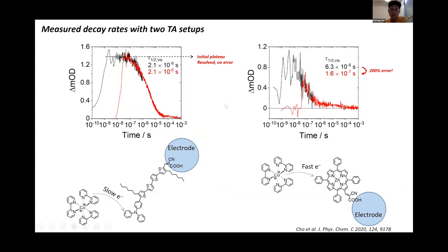This model was tested using actual donor-acceptor pairs. First, I chose one acceptor molecule decorated with an alkyl chain, which is an insulating layer blocking the charge transfer reaction, so electron transfer is normally slow. Using those two setups, shown as the black and red curves respectively, both were able to resolve the initial plateau. So there is no difference in the decay rate determined by the T1 half, which is the time it takes for half of the initial signal to decay. There is no difference in this slow case.